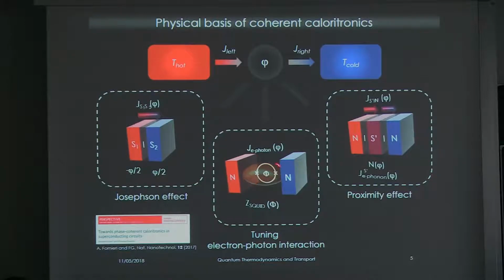Thanks to this coupling, by changing the resulting impedance of this object with respect to the magnetic environment, thanks to the flux, we can control how the two reservoirs interact in terms of the exchange rate of energy of one with respect to the other. And so this can be a very effective way of controlling the heat transport from one side to the other. In this tutorial, I will concentrate mainly on the first part, showing just some of the other two paths in order to give you an idea of what has been done and what is going on.